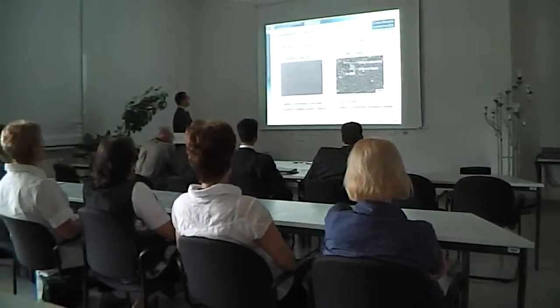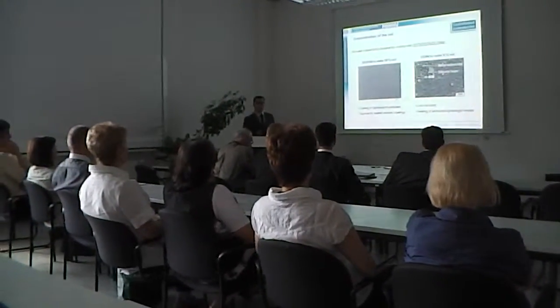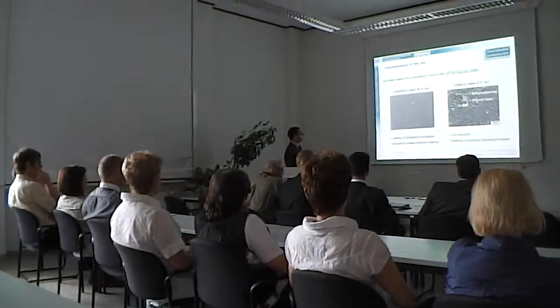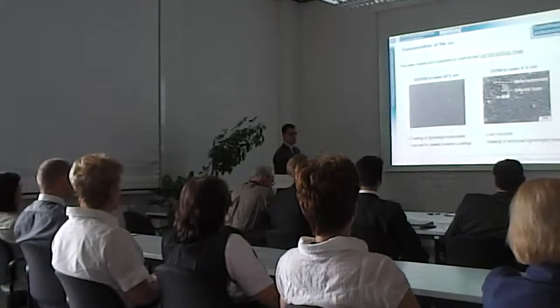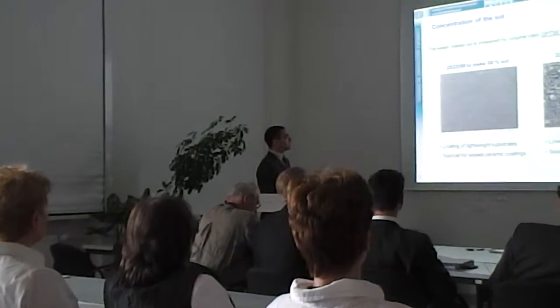Other concentrations were tested, 20, 30%, and 50%, which is prepared by this ratio, has the best corrosion protection. It's clear here from the scanning electron microscope for the surface of the sample. The film completely covers the surface, and the samples coated with this film have much better protection than these samples.